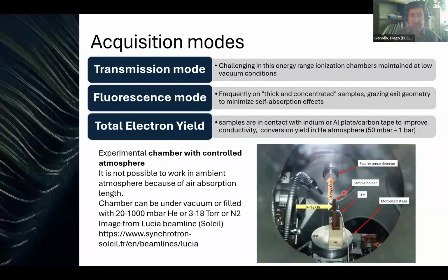One would be a transmission mode that is much more challenging than for hard X-rays because, as I said, the sample needs to be very thin, and also the ion chambers need to be maintained in some controlled atmosphere, possibly with low pressures, to avoid having windows and then keeping them at the same pressure of the chamber.